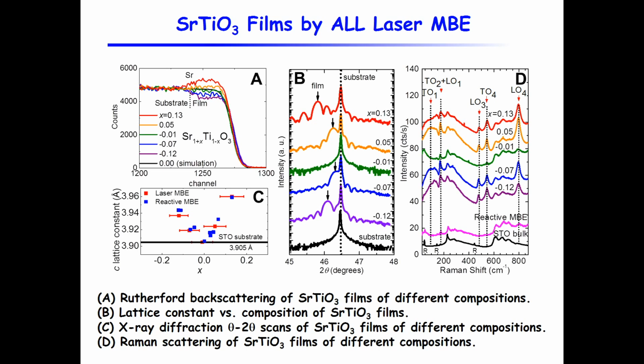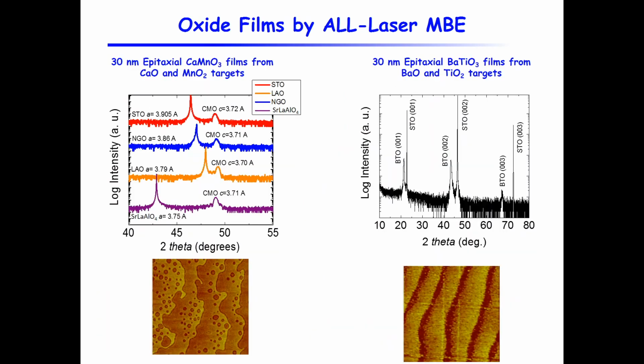And X-ray diffraction is to look at one of the peaks. This is from the substrate. This is from the strontium titanate films. You'll see that if it's off stoichiometric, you will see the film peak that's different from the substrate peak. And when they are close to stoichiometry, you cannot really distinguish them. And this UV Raman also shows that the symmetry breaking is minimum when the stoichiometry is achieved. So this is strontium titanate. We've demonstrated that also in calcium manganite and barium titanate. And so the technique is quite versatile for different materials.